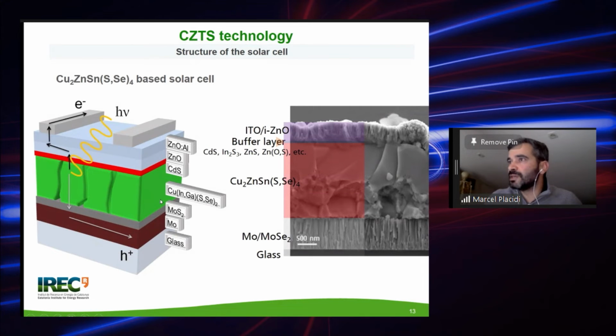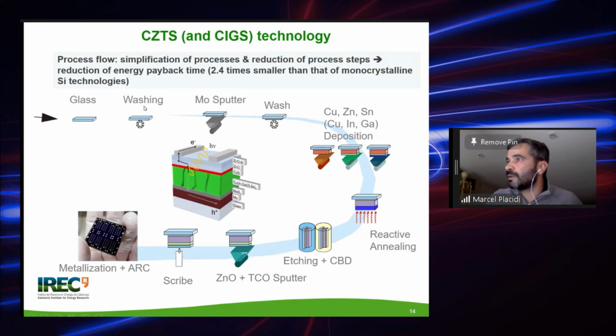So here in this figure, we can see the typical structure of a kesterite or chalcopyrite solar cell. It's exactly the same. We replace the CIGS absorber by a kesterite one. You can see the back contact, the front contact, and here an SEM image showing the different layers. Okay, in this slide, we can see the entire fabrication process with all the different steps. All of them can be done in a lab without any cleaning condition required. I mean, there is no need to make them in a clean room, for example.